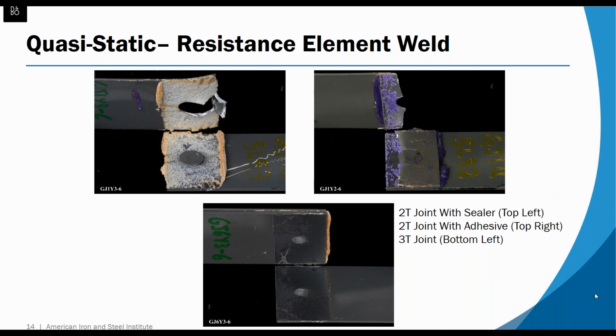In the upper right with structural adhesive, we actually see a failure at the interface to the joining element rather than in the top sheet because there's a stress riser there. Then in the bottom sheet, the failure mode is a little bit different than the resistance spot weld baseline because we are cracking through the weld surface instead of pulling a nugget out of the bottom surface.